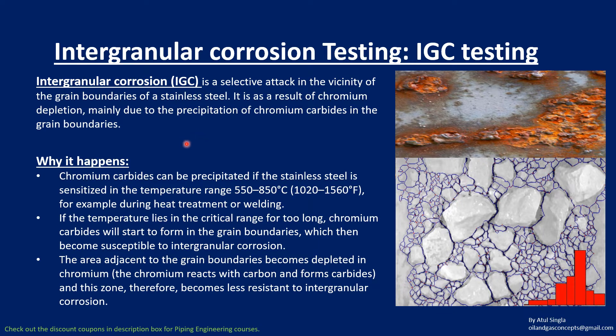This sensitization can occur during welding or heat treatment processes, even when we are not designing for such high temperatures. Stainless steel may pass through that temperature range during those operations. Chromium carbide formation occurs if the steel remains in this critical temperature range for too long — a momentary exposure is acceptable, but prolonged exposure causes chromium carbides to form at the grain boundaries.